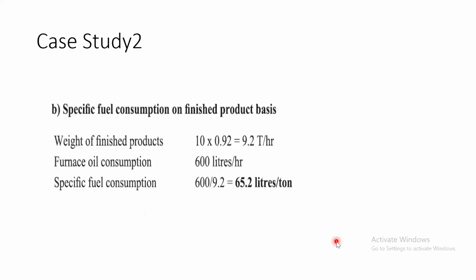Yes, sir. Clear. Okay. Now we talk of specific fuel consumption on finished product basis. So weight of finished products is nothing but 10 ton per hour, and 92% is the percentage yield. So ultimately at the end of the process, though your input is 10 ton, you get melted metal in terms of 9.2 ton per hour. So the rest of the 800 kg is nothing but slag, for your information, which we studied in the previous slide. So slag has formed in the balance 8%, right? Now furnace oil consumption is 600 liter per hour, and this has to be converted into specific fuel consumption, because 600 liters of oil is required for melting 9.2 ton of effective output material. So 1 ton needs 65.2 liter of furnace oil or FO.